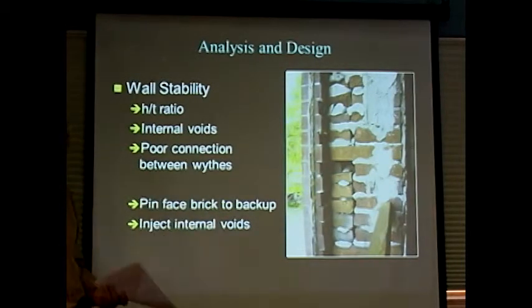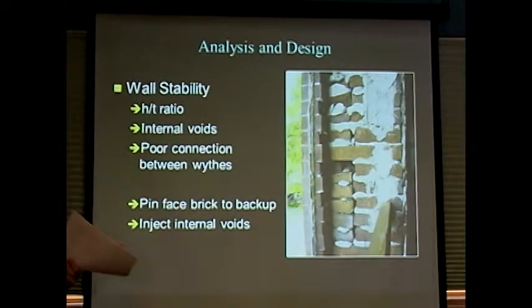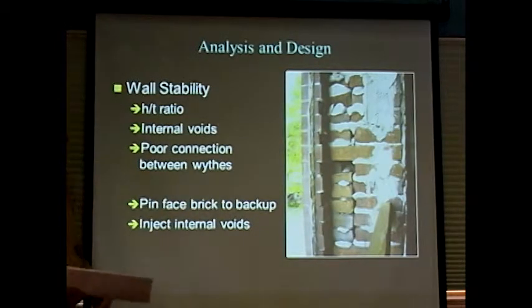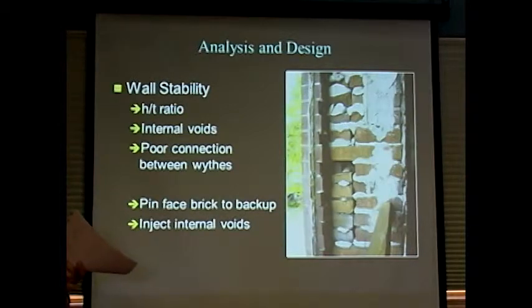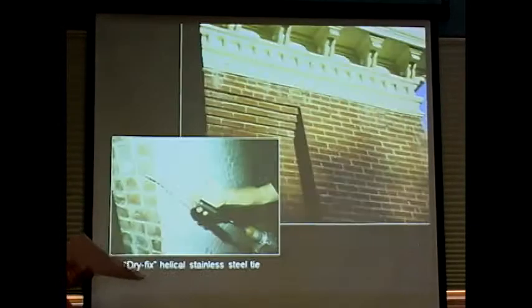Remember, they're taking out all the interior floors, all the interior bearing walls. They can't do that without having monolithic action between all four wythes. So we came up with a recommendation to pin the face brick to the backup where the blind headers were missing, and then injection to fill these internal voids.